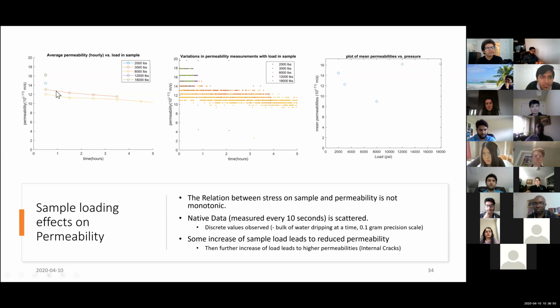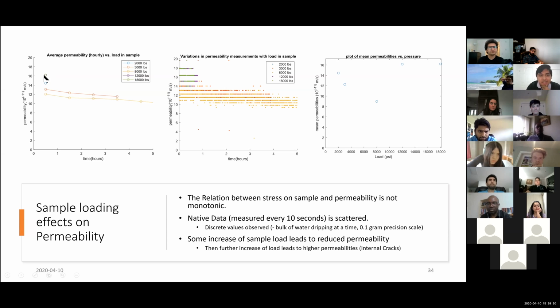So here, first I compared all those values for 1 hour, and then I let some of those tests go a long time. So we can see that initially there is a higher permeability with less stress, and as we increase the stress, the permeability goes down, and after a certain value, it rises back up again. So we can see a higher permeability once we go past this value.